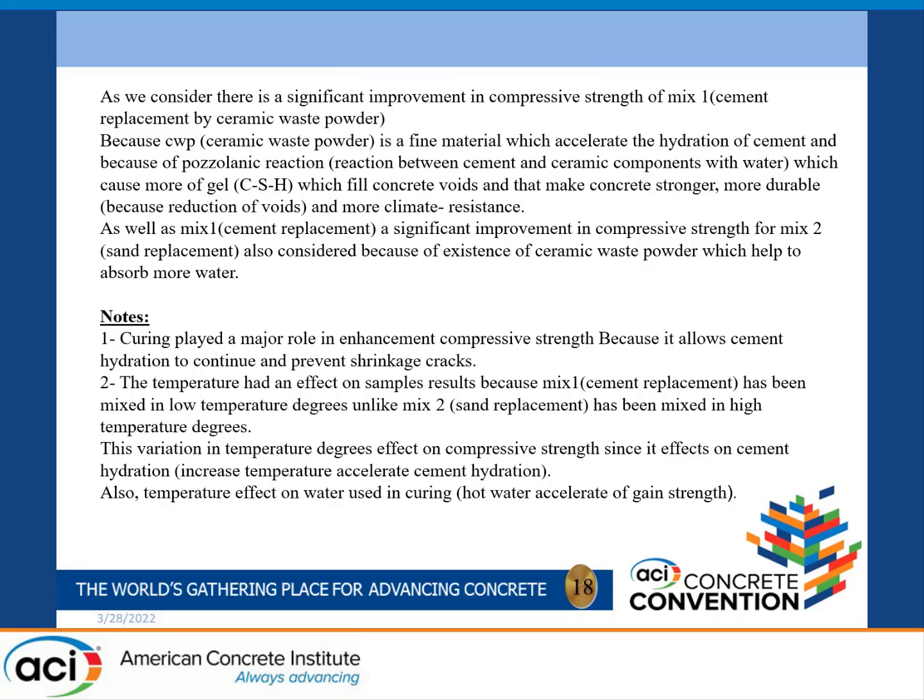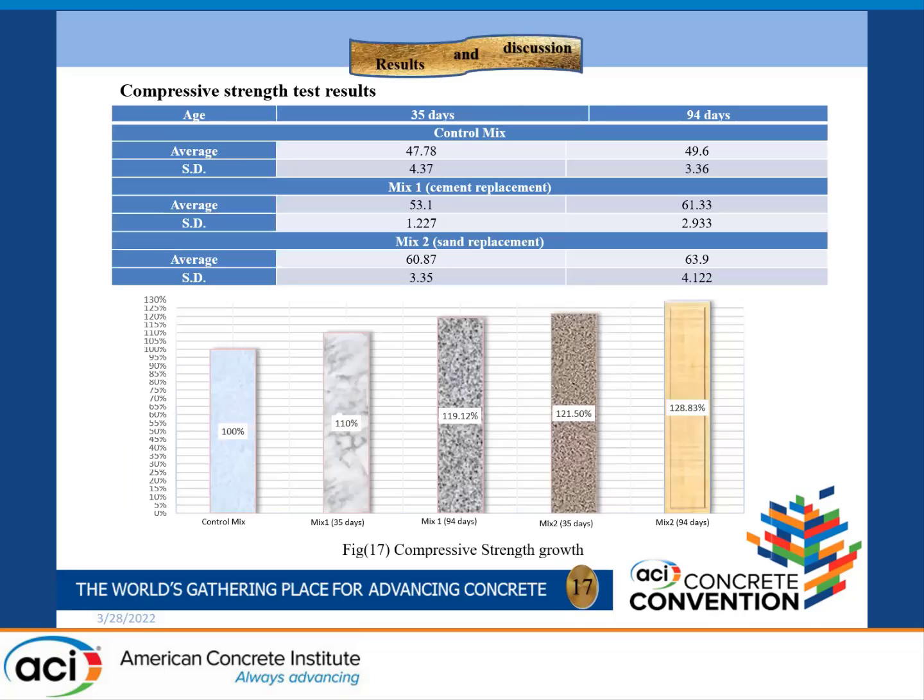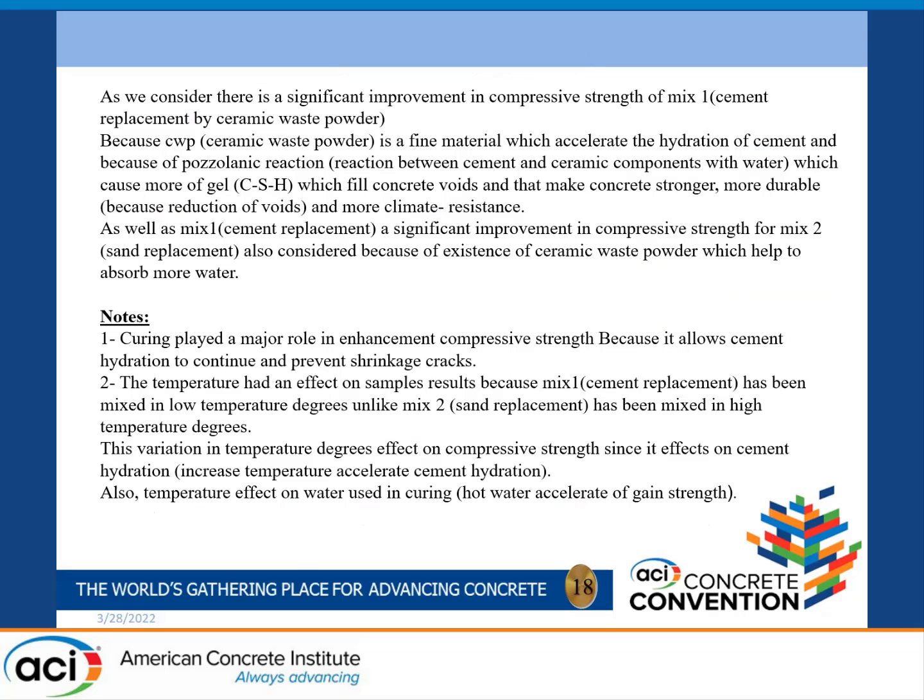Also the second mix, which is sand replacement, gives us higher compressive strength because the ceramic waste powder is a very fine material which helps to absorb water. There are some notes I want to take into account: curing played a major role in enhancing compressive strength.